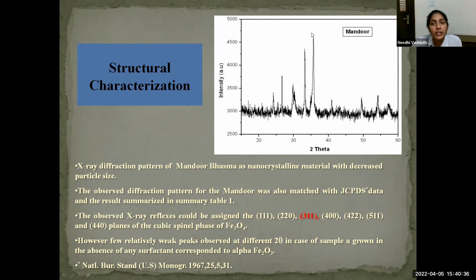We see the maximum intensity. This peak shows maximum intensity, and that is 311. As we observe, the diffraction pattern of Mandoor Bhasma was also matched with JCPDS data, and the result is summarized in Table 1, which is given below in the next slide.